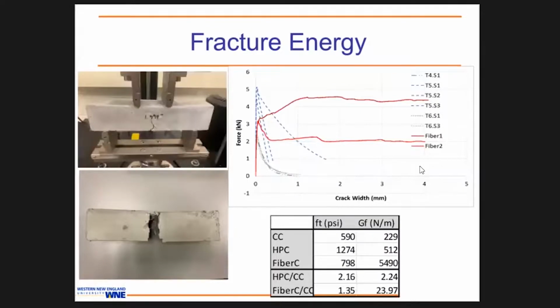And now we added the fibers. So you have the red line and a slightly darker red line, which are with fibers added to the conventional concrete. As you can see, the fracture energy, which is the GF value in Newton per meter, normalized by the area of the crack surfaces, is significantly increased. That is 5,000 or 5,500, where CC, or conventional concrete, is about 250 or 229. So that is a significant increase.